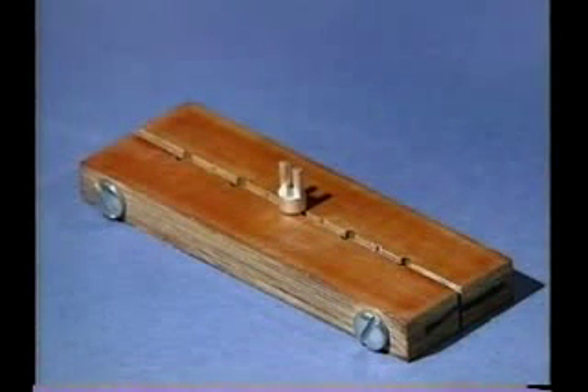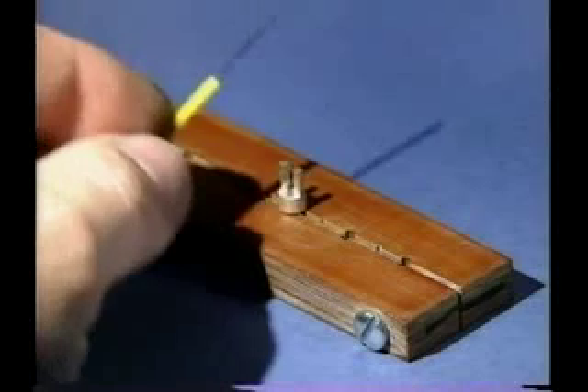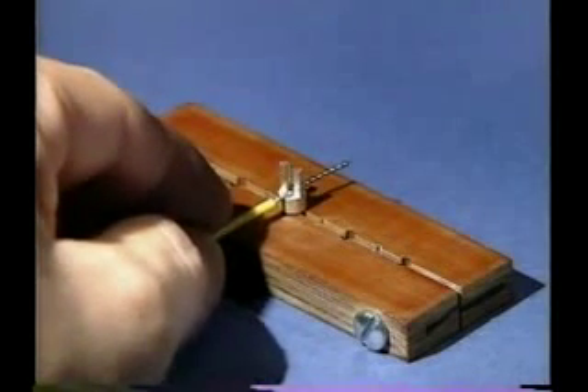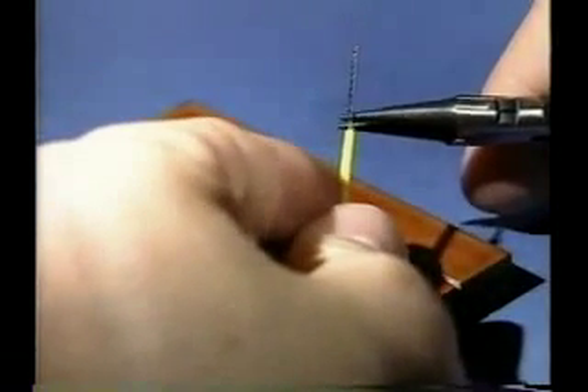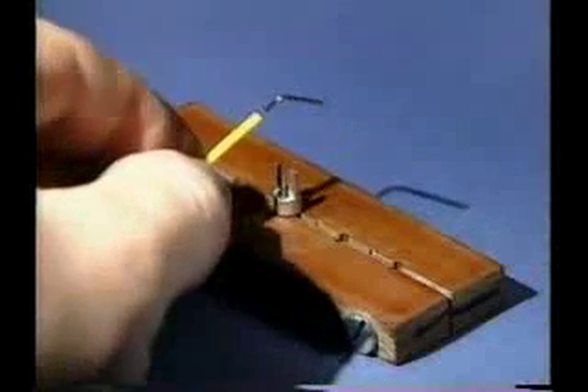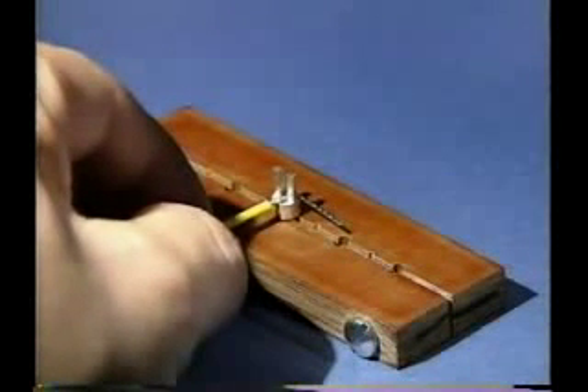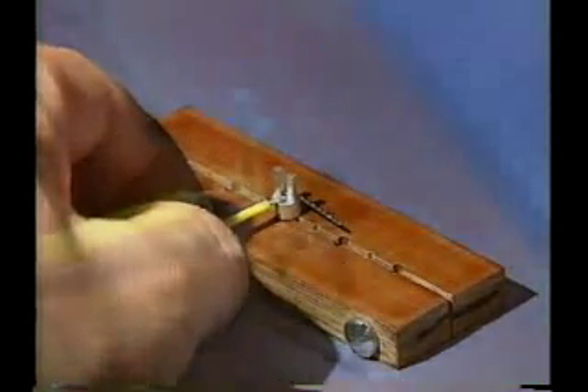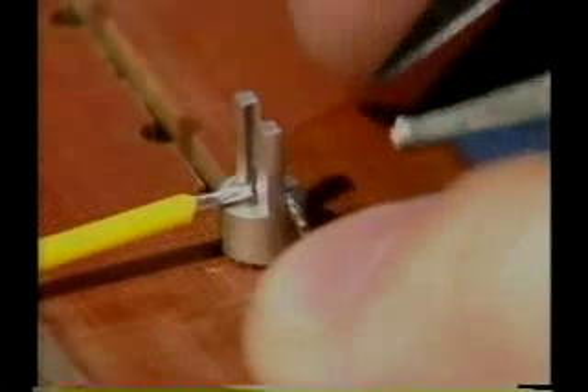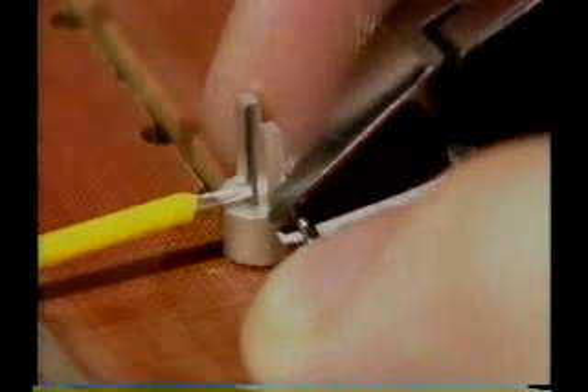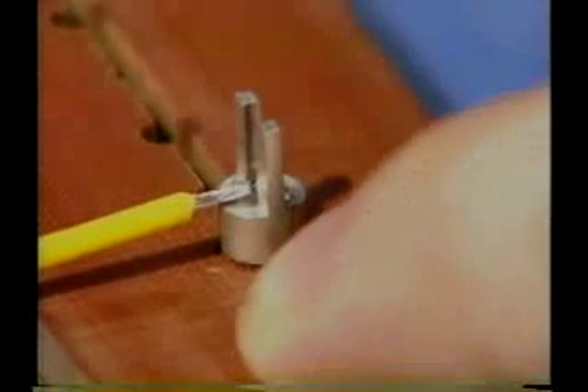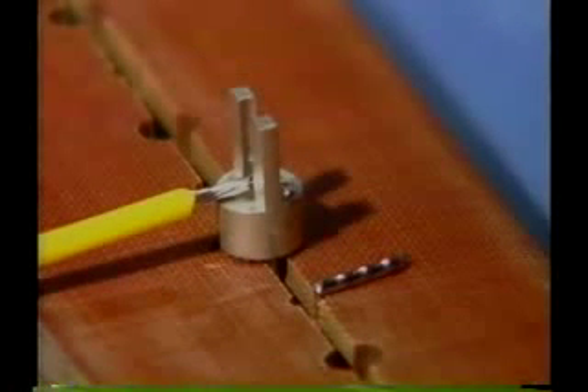Let's watch the soldering operation. The pre-tinned wire is laid across the terminals to determine the proper insulation clearance. A 90-degree wrap is made using pliers that are not serrated so damage will not occur to the wire. The wire is now positioned and trimmed so that it doesn't protrude beyond the diameter of the terminal. It should contact the middle side and the vertical edge.